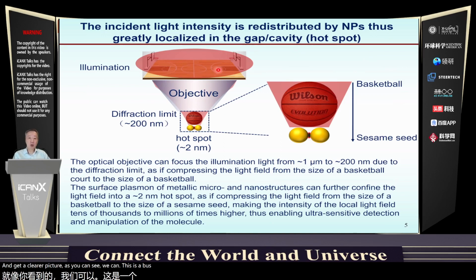And in order to give you a clear picture, as you can see, this is a Gaussian beam field, very big. Then through this objective, we can get a focused laser spot, about 1 micron to 200 nanometer. With this nanoparticle, we can further reduce this light and mainly concentrate it at the gap, so that we can reduce it to 2 nanometer in diameter. Please pay attention to this size, which is very useful for interacting with molecular science, because this is the size of a molecule.